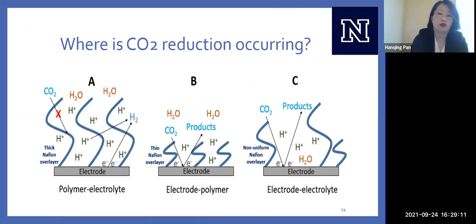So these set of experiments really helped us answer the question of where is our CO2 reduction occurring? So let's think about a couple scenarios. The first thing that could happen if we have a really, really thick Nafion overlayer, 100 microns, 200 microns, nothing can diffuse through. CO2 cannot diffuse through. The only thing that could happen is protons from the electrolyte and electrons from our metal surface combine and make hydrogen gas. And this is exactly what we're seeing experimentally. With a really thick Nafion overlayer, the only product we're seeing is hydrogen. And so the reaction is happening up here on top.